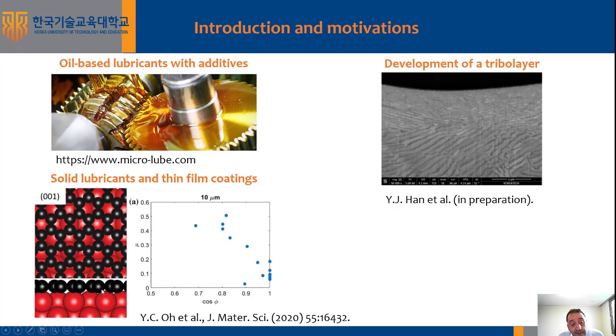However, we need to keep in mind that the lubrication effect of graphene really much depends on the orientation of the underlying substrate. So we showed recently that when there is good registry of the graphene lattice onto the lattice of the substrate, the friction coefficient of graphene is indeed very low. However, once we lose the commensurability between graphene and in that case copper, the friction coefficient increases dramatically. The reason for this is as soon as we lose registry between graphene and the copper lattices, we in fact increase the likelihood for the formation of folds and the activation of the puckering mechanism.